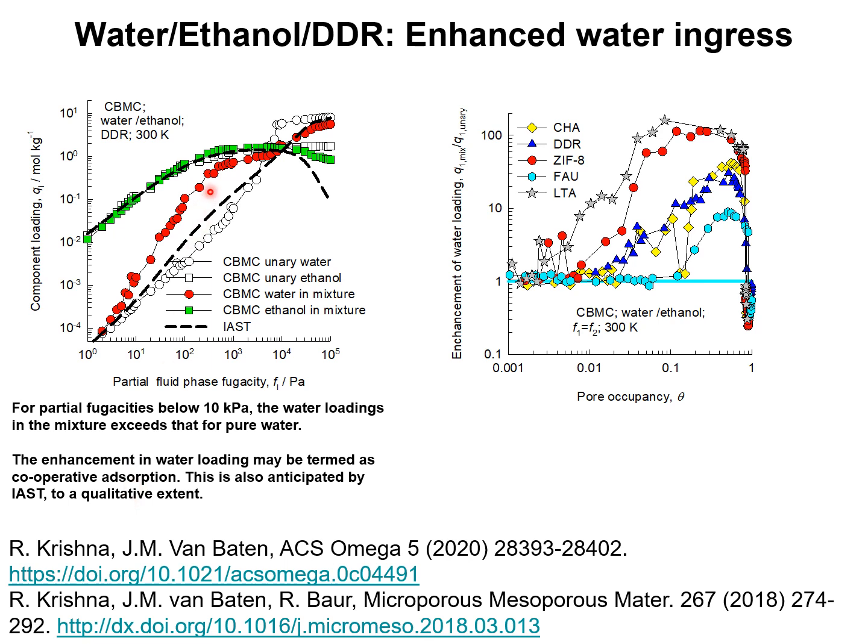This phenomenon, in which the component loadings in the mixture are higher than the pure component loadings compared at the same partial fluid phase fugacity, is called cooperative mixture adsorption.